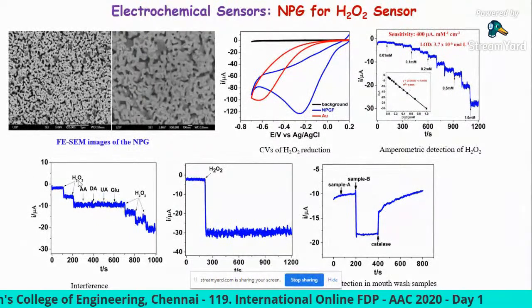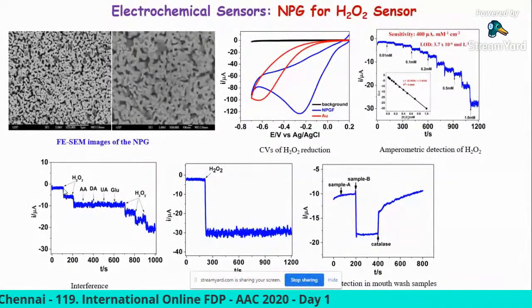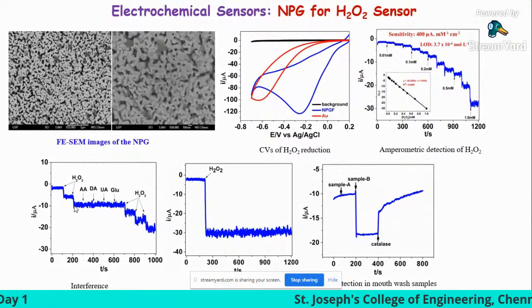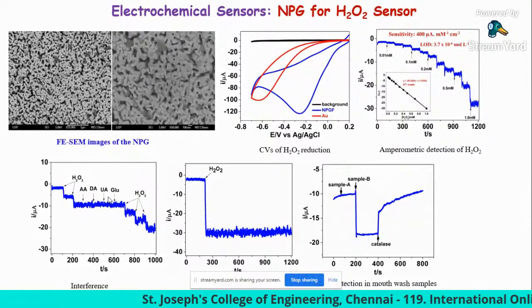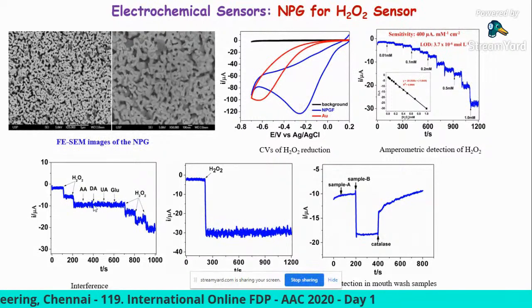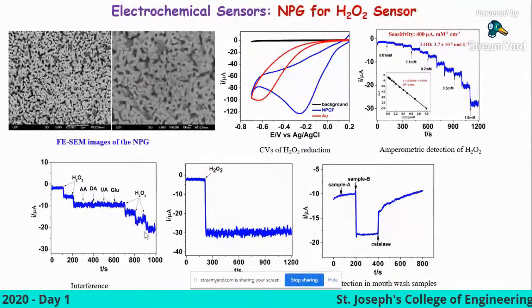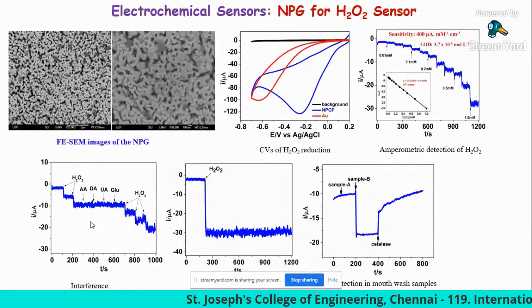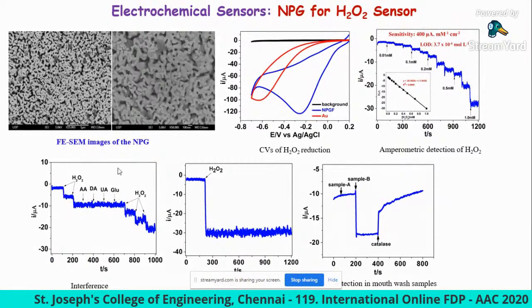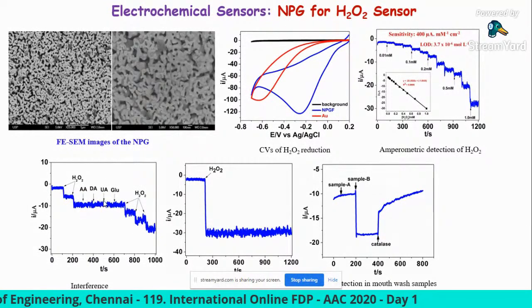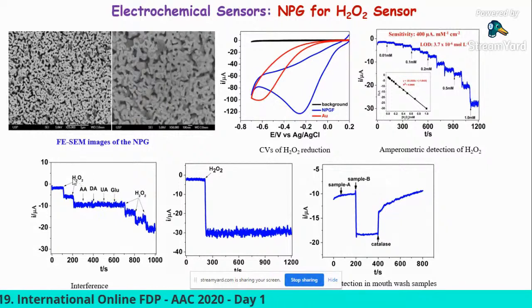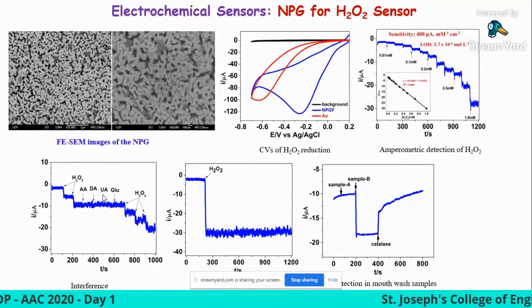Here you can see the current signal is increased whenever you add hydrogen peroxide. If I add hydrogen peroxide, the current signal is increased. Here, the current signal is increased. However, if I add the ascorbic acid, dopamine, uric acid, glucose, the current signal is not increased. Then later on, if you add the hydrogen peroxide again, the current signal is increased. So this data clearly shows that one can use this nanoporous gold as a sensor to selectively detect hydrogen peroxide even in the presence of other substances.